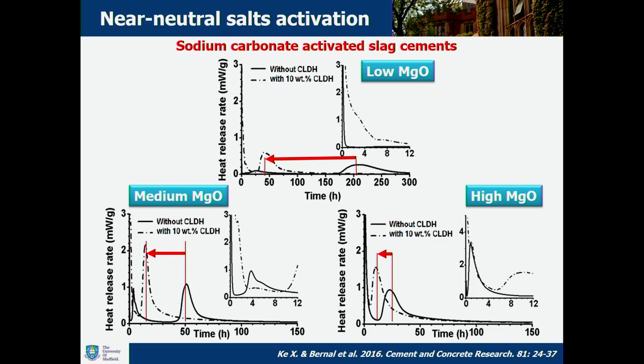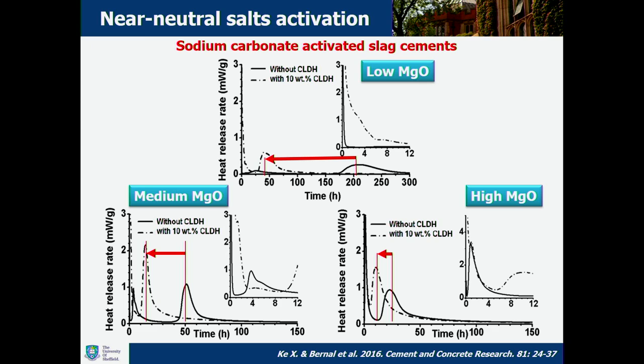So we can see in this isothermal calorimetry how including this layered double hydroxide significantly modifies the kinetics of reaction. This effect is more notorious when we have slags with low magnesium content, and of course, the effect is less notable when we have high magnesium contents within the slag. What is really interesting here is that if we match the right activator to the right slag, we can produce a material with the desirable properties we want to achieve.